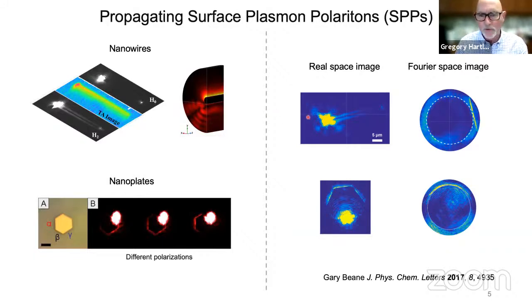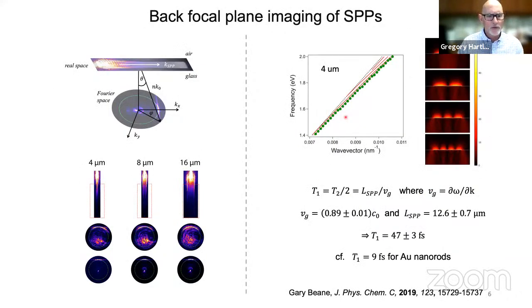So rather than use chemically synthesized materials, what we did here is we did some photolithography to make structures that all had about the same thickness, and that makes the experiment a lot easier. So these are some images of our structures. We call them nanostripes. They're about 50 nanometers thick. They have different widths and they're all about 100 microns long, right? So they're really long. The length doesn't matter here.